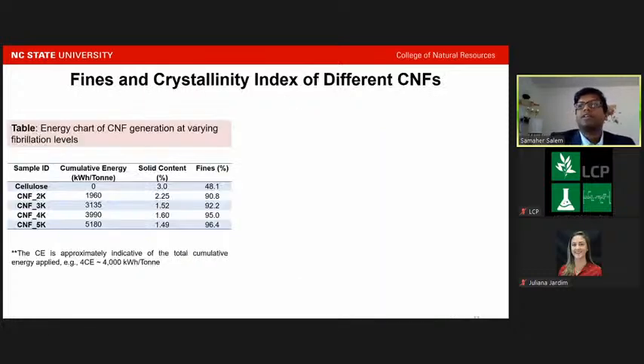So the fines content and the associated available surface area increased with the increase of energy supply, due to delamination of the cellulose to nanocellulose. And you can see, as we put more and more energy, which is denoted by 2K, 3K, 4K, 5K, that is 2000 kilowatt hour per ton, 3000 kilowatt hour per ton, we could say that the fines content increased, which shows how the nanofibrils have been produced from the cellulose fiber.